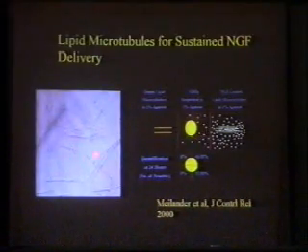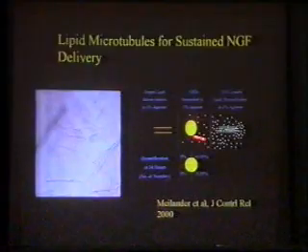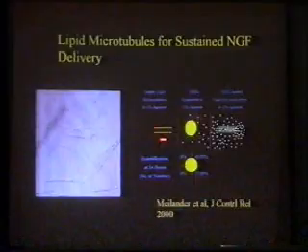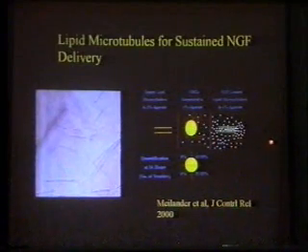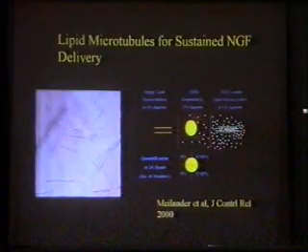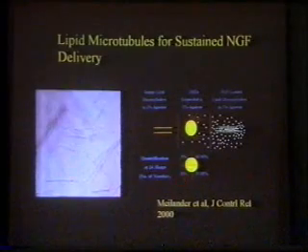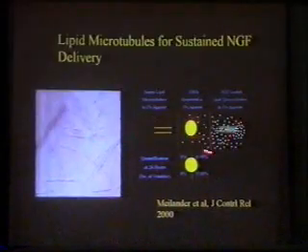So if you make those things and load them up with nerve growth factor, and take a gel and make 3 layers of a gel. On one side, we put saline-filled tubes. In the middle, we put the dorsal root ganglia. On the other side, we put these microtubules, or loaded straws, with nerve growth factor. And we show that we can implement the chemotactic design in vitro by seeing that all of these things grow if you capture them at the right time. I'm sorry that you can't see the blue very well, but essentially 100% grow this way and not this way because of the chemoattractive effect.